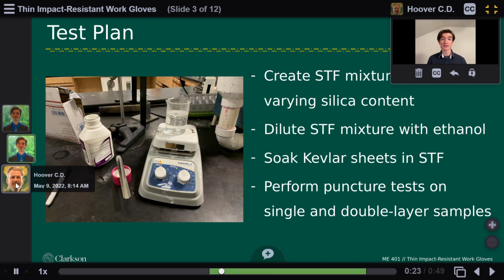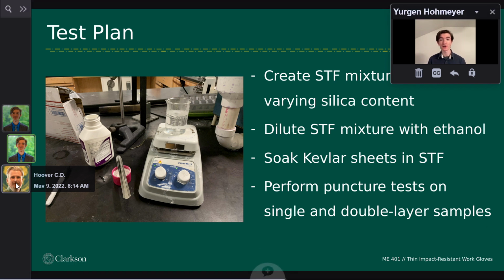Our test plan involved creating different shear thickening fluid (STF) mixtures with varying silica content by weight. These mixtures were then diluted using ethanol before Kevlar sheets were soaked to impregnate them with the STF. Finally, puncture tests were performed to determine the force required to puncture a single or double layer of STF-saturated Kevlar sheet.